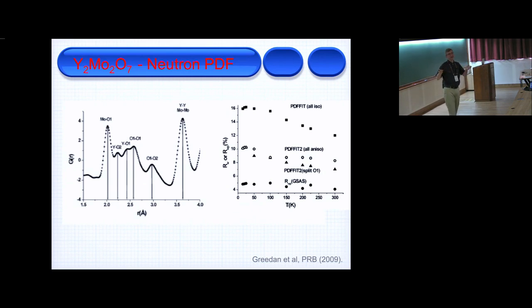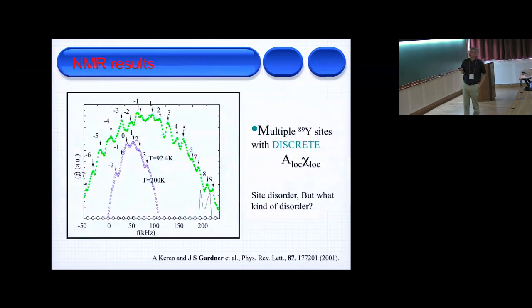As we cooled down, we don't expect a structural phase transition. We haven't seen one. So we think what's happening is the magnetic interactions are becoming involved. You're getting correlations, and then you have magnetoelastic effects, and these bond lengths start changing. In NMR, another local probe with yttrium, these peaks, if it was a nice, wonderful system, should just be a simple Gaussian, a nice, smooth curve. But with NMR, we saw as you cooled down, there was actually structure to these curves. And at the lowest temperature of this data set, you had many peaks. So this was telling you that around every yttrium, there were discrete, because these are nice peaks, it's not just a big blob, discrete positions, the different internal fields well defined.